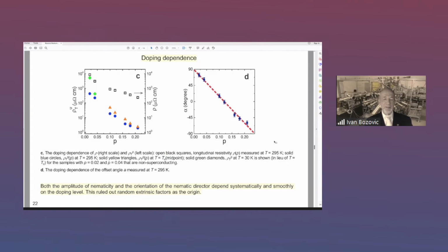To show that this is not indeed the case for the nematicity we observe, there is a simple argument, which is a doping dependence. We studied many films, thousands of films, and they are all patterned with the same lithography mask, which means that the contact misalignment must be the same in every film. However, we found that both the amplitude of the nematicity and the orientation of the nematicity actually depend on doping strongly and systematically and smoothly.